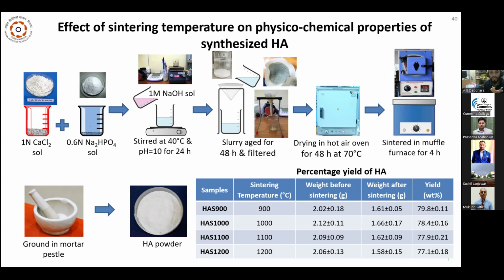After mixing for 24 hours, it is filtered using filter paper and washed using distilled water to obtain the precipitate. Then it is dried in an oven for 48 hours at 70 degrees Celsius. To observe the effect of sintering temperature, the samples are sintered at different temperatures, which are 900, 1000, 1100, and 1200 degrees. After sintering, it is ground using mortar and pestle to obtain the fine powder. After the synthesis procedure, it is observed that the maximum yield is obtained at 900 degrees Celsius, which is obvious because of the low temperature compared to the others.